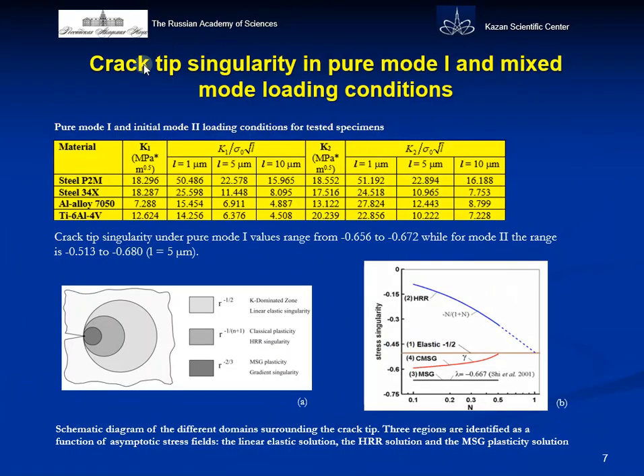The next slide presents an analysis of the singularity-exponent behavior for asymptotic models of the crack-tip stress fields. Three different domains surrounding the crack-tip can be identified as a function of asymptotic stress fields: the linear elastic solution, the HRR solution, and the MSG plasticity solution. Line 1 corresponds to the elastic solution, line 2 represents classical plasticity, line 3 is obtained from the analytical solution of the gradient plasticity, and line 4 corresponds to our numerical result with CMSG. These graphs are presented as a function of the work-hardening exponent for a material structure parameter of 5 micrometers. In our calculations, the intrinsic length of the material varied from 1 to 10 microns.